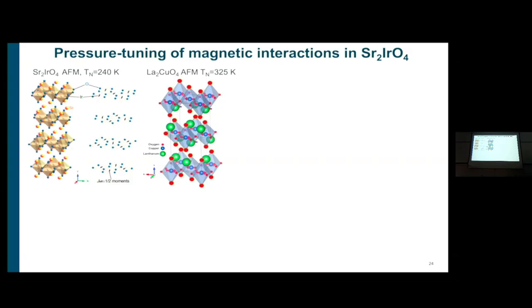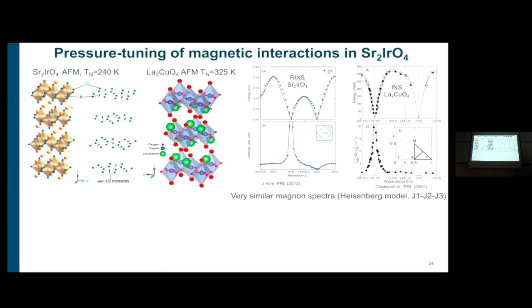Okay, well, maybe just very quickly, I'll go very briefly. This is another example where everything comes together. This is where we use XMCD and resonant magnetic scattering, and you need both techniques to actually understand what's going on. It's the 214 system. I think everybody's familiar with the cuprates, the parent compounds of the high TC superconductors. This is an analog based on iridium. They have both this G-type antiferromagnetic structure, although this one has rotation, so you see the spins are rotated due to the Dzyaloshinskii-Moriya interaction. But incredibly enough, although this one has a very big spin-orbit coupling in the iridium 5D moments, the magnetic excitations are almost identical.